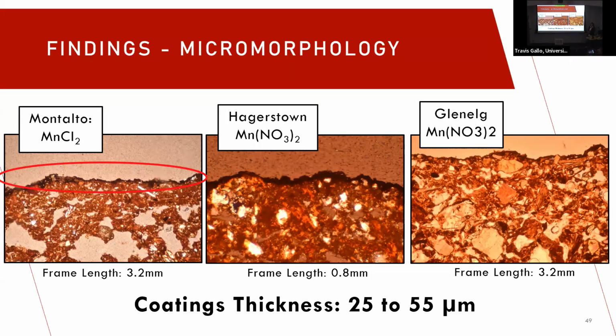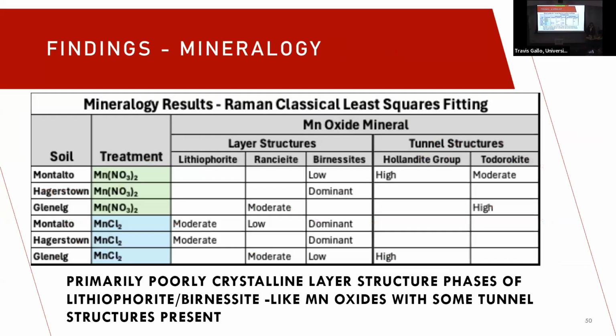Here are some pictures of the micromorphology analysis. We primarily use thin sections to determine coating thickness, and we determine them to be 25 to 55 microns thick. And you can see the coatings that were formed on the surfaces of the 3 strongly expressed samples. Here are the mineralogical results for the soil treatments that formed the strongly expressed coatings. Through Raman spectroscopy, we were able to determine that they were primarily poorly crystalline layer structure phases of lithiophorite, birnessite-like oxides with some tunnel structures present.